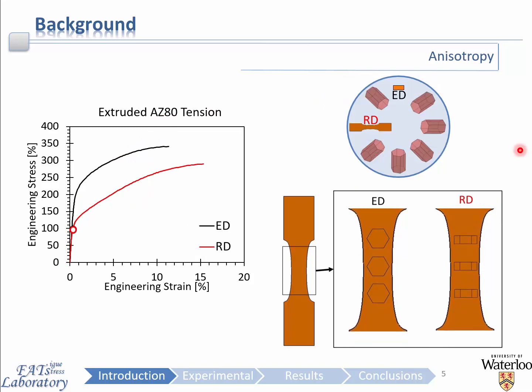Anisotropy is also another well-known phenomenon which is present in most wrought forms of magnesium alloy with sharp texture. In essence, it describes the dependence of the material properties on the direction relative to the crystallographic axes. Take now, for example, these tensile dog bones that were taken from an extruded billet of magnesium in the extrusion direction here and the radial direction here. It is well known that AZ80 magnesium extrusion has its crystals oriented such that the C-axis is in the radial direction, as shown here.